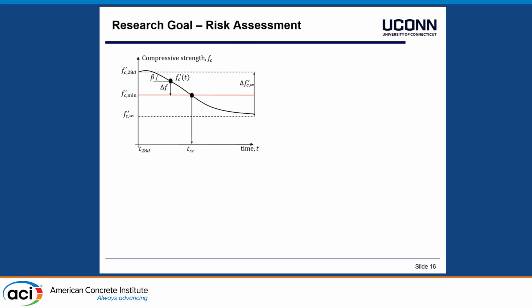So the idea in terms of risk assessment is what value might be most important for the integrity of a foundation or the house structure. And one parameter which comes to mind, or might be important, is the compressive strength, right? So if we start off with mixing the concrete, you have a certain compressive strength, and then there's a certain minimum compressive strength, let's say 3000 psi for a foundation wall. And you have certainly over-designed this, but over time, if you have deterioration, you might cross this limit. And then the question becomes of concern in terms of structural integrity of the structure. So what is this time? Would we reach the minimum strength at all or go under this?